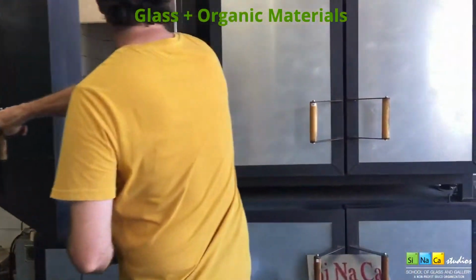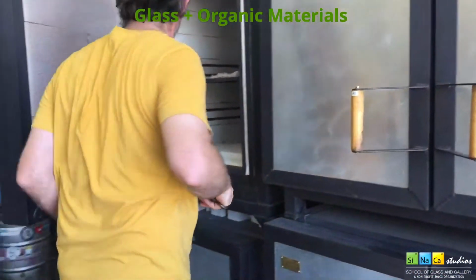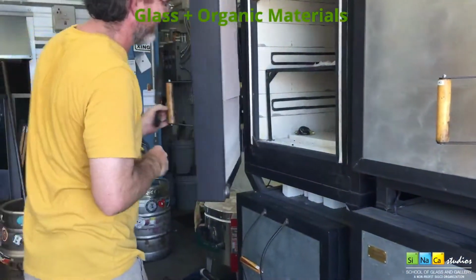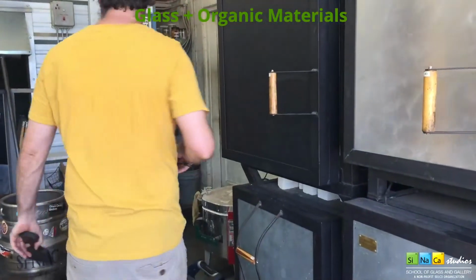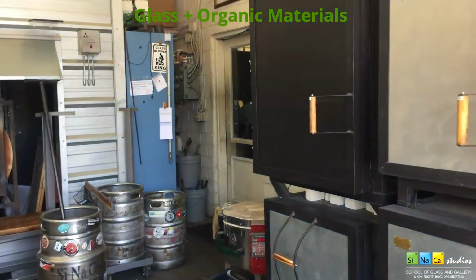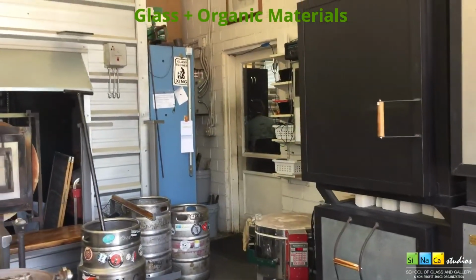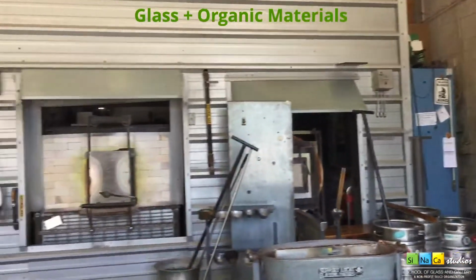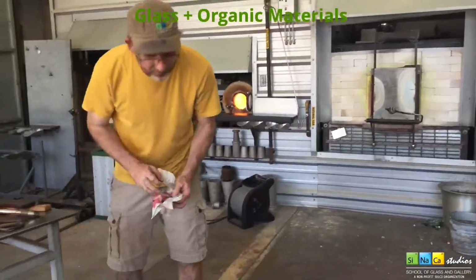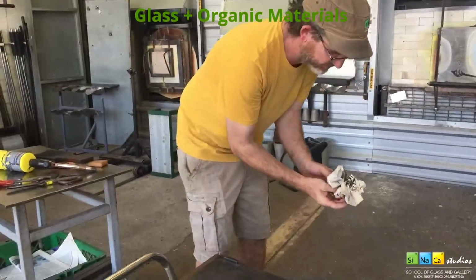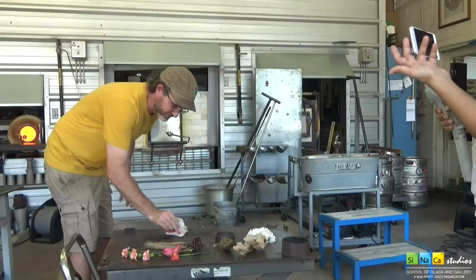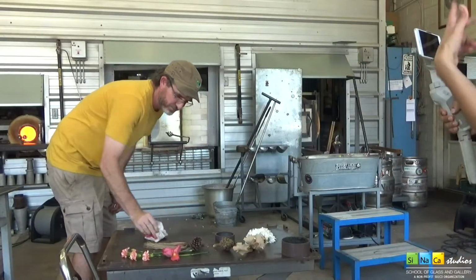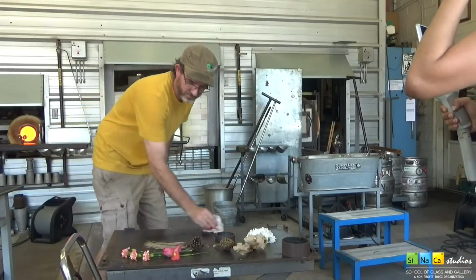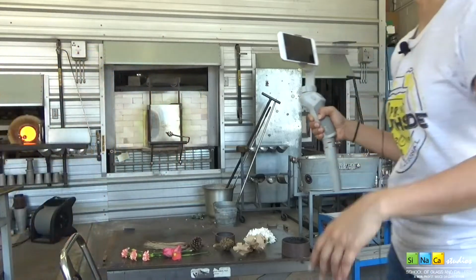So Clifton's putting it into the annealer, and that annealer is going to make sure it comes down nice and slow, down to room temperature. That annealer is sitting at about 900 degrees or so. So when we're putting these things away, we've got to make sure it doesn't cool too fast down below that temperature. Otherwise, we'll experience cracking of the glass, which is what we're trying to avoid.